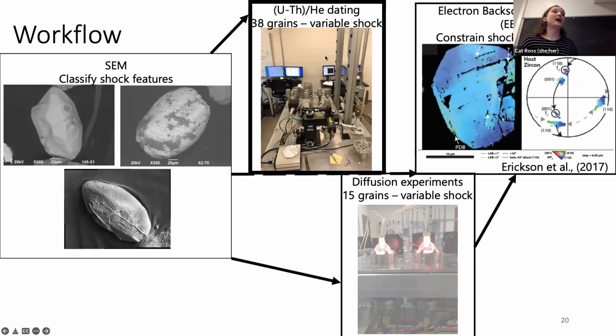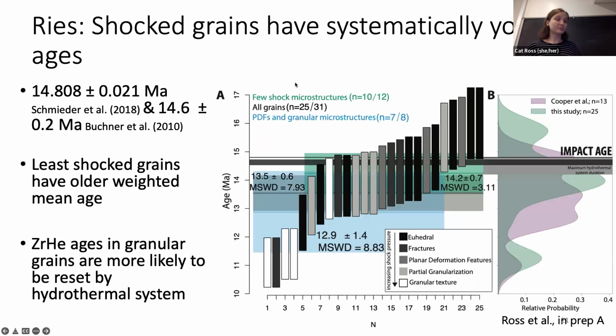So now I'll talk about just our zircon ages that we have obtained. This is predominantly from the Ries impact crater, so it's the younger one in Germany. And what you can see here is that the least shocked grains are older than the most shocked grains. So each of these bars is a single zircon crystal, and they're colored by the shock textures. So lighter ones are the highly shocked grains. And if we just take a weighted mean age of the least shocked material, we get an age that's closer to the impact age, within error of the impact age from the argon-argon constraints.